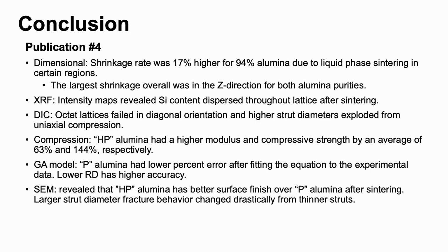So in conclusion for the publication, we saw that as far as dimensional analysis, the shrinkage rate for 94% alumina was higher than the 99% alumina due to it being less pure. Since it was less pure and it had elements such as magnesium, calcium, and silicon, it induced liquid phase sintering in certain regions. When we looked at the XRF results, we saw that the intensity maps revealed silicon content was dispersed throughout the lattice after sintering, although we did see some instances of silicon agglomerates.